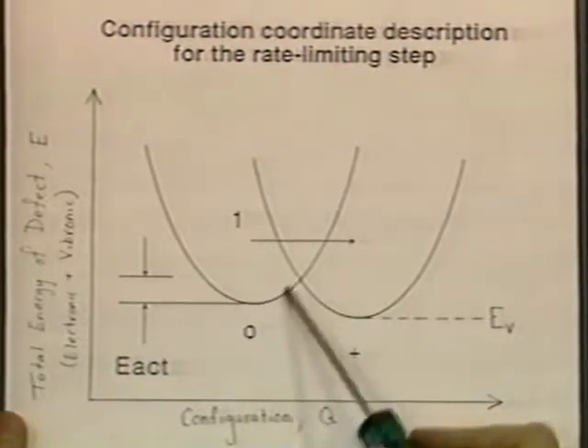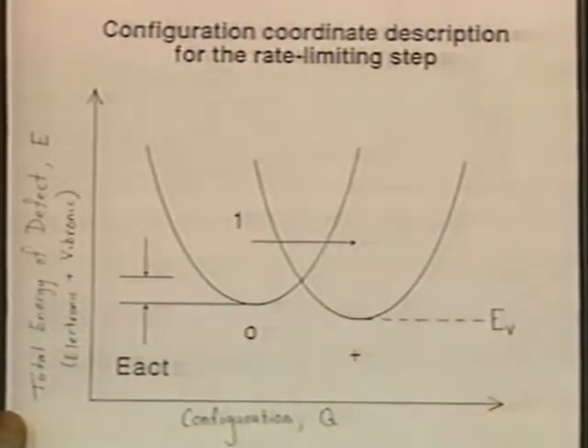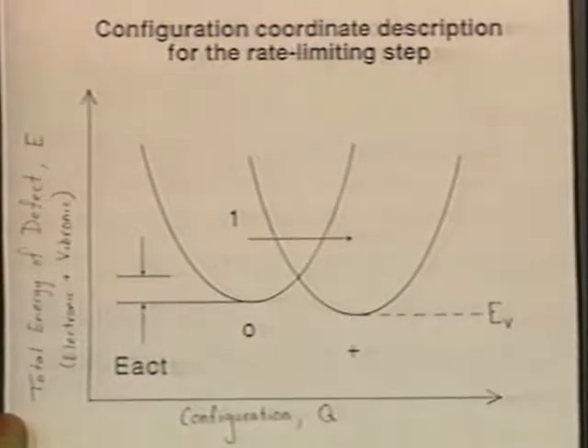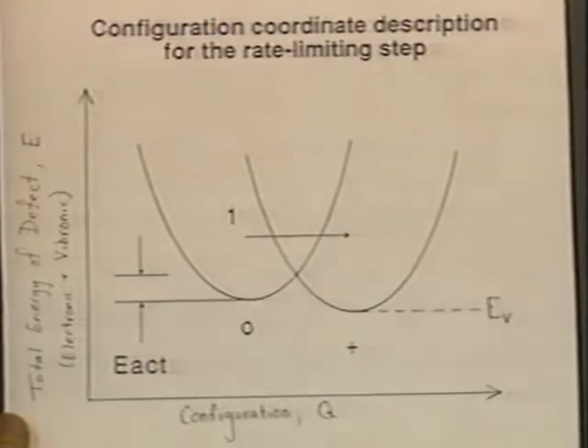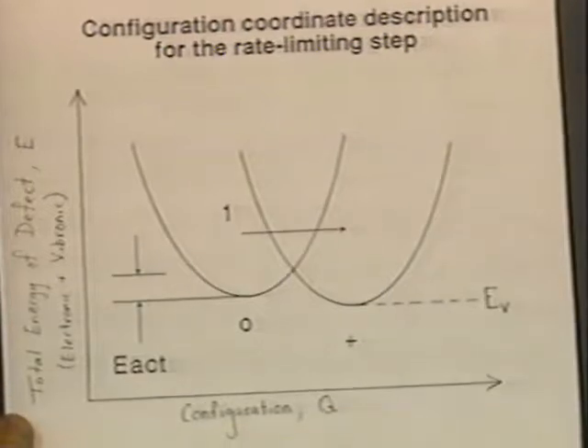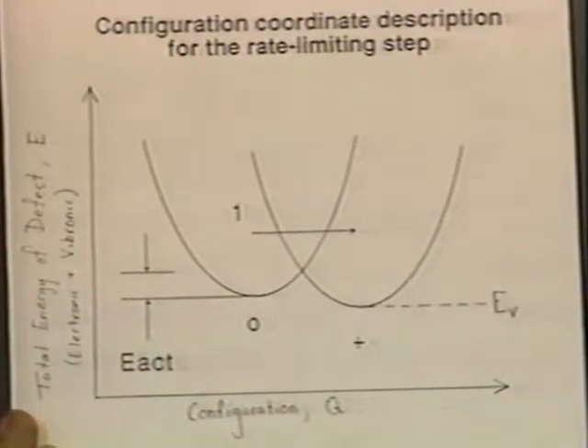And in order to get this vibrational energy, that's temperature. You need to be thermally excited. So you've got thermal activation at high temperatures, and if it's a defect that's in close proximity to the silicon surface, you could have tunneling, either tunneling of the electron or configurational tunneling at low temperatures. And that, I believe, is what's taking place. And this is stuff I studied for my PhD thesis a long time ago, and that's the information I bring with me into this field, is that I think a model like that is more appropriate, though I'm just beginning to come up with the model for what's happening.